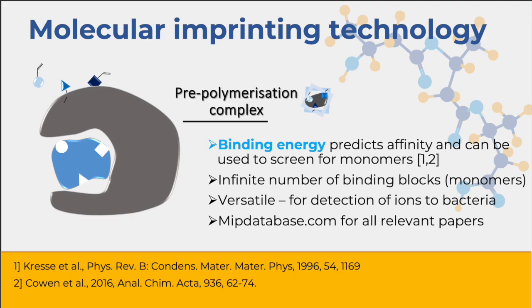Let's have a brief recap of what molecular imprinted polymers are. In essence, you start off with a template or a target molecule, you assemble functional monomers around it that can interact via a range of non-covalent interactions such as hydrogen bonds or ionic interactions, then we polymerize it to lock it into place into a 3D matrix, and then we finally extract the target. What you end up with are porous structures containing high affinity binding sites. What has been well established is that the final affinity is governed by the pre-polymerization complex — the complex formed when your target has monomers assembling around it.